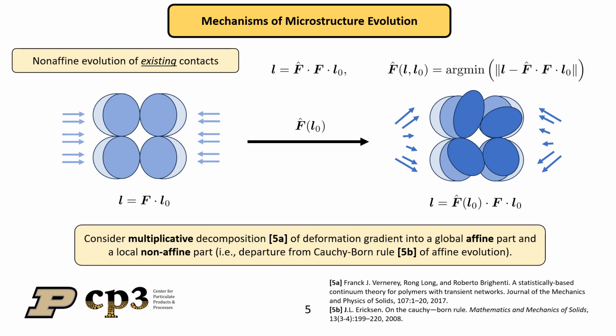To that end, we propose a multiplicative decomposition of the deformation gradient into a global affine part and then a subsequent local non-affine part. One key point to make is that this is a departure from the Cauchy-Born rule that has often been used to assume that the microscale deformation of a system follows the overall deformation gradient, and we instead determine what the local non-affine field is as a function of the microstructure.